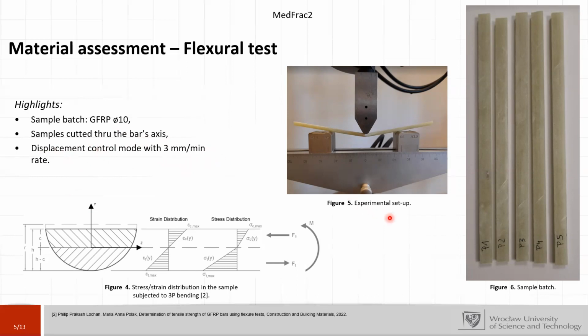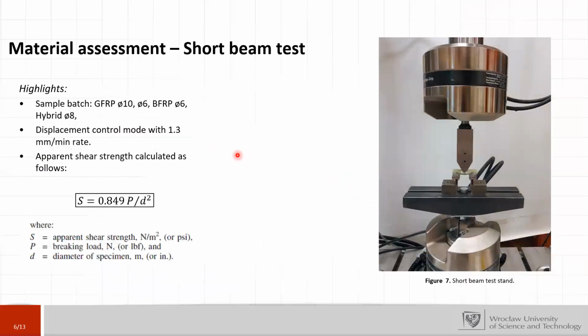Okay, then short beam test. So here we use more samples. So GFRP with 10 and 6 millimeter of diameter, then basalt fiber reinforced polymer, and the hybrid one. And the hybrid one is with 8 millimeters of diameter. So the displacement control mode with 1.3 millimeters per minute, and we calculate the apparent shear strength as it is presented here. That's the formula for this, where P is the breaking load and D is the diameter. Here we can see the test stand.